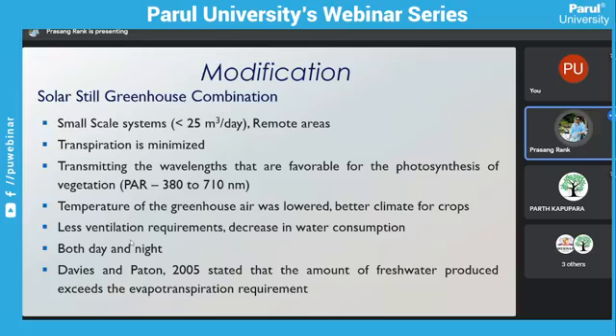The inside temperature will get minimized due to the solar still at the top. The inside temperature will be optimum, so transpiration will get reduced. And also it is used in small scale systems only, because at the top we can't use a heavy system. So 25 meter cube per day or less only we can use, and also in remote areas. The wavelength transmitted in the greenhouse is the photosynthesis wavelength from 380 to 710 nanometer. The temperature of water at the top won't be much, and the efficiency won't be as good compared to the other types. But the temperature inside the greenhouse will be lowered, and the climate inside the crop will be better. So we won't require any ventilation, and also water consumption of the plant will reduce because the transpiration is reduced. So in this way, this solar still greenhouse combination can be very useful.